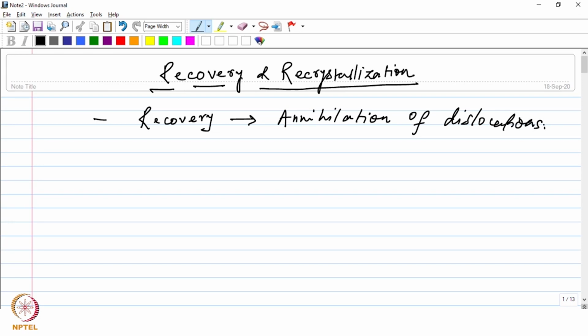When the dislocations get arranged in some low energy configurations, the dislocation density is going to reduce, and the regions around this arrangement will be free of dislocations, right? So that's how the recovery occurs as you heat the material to some elevated temperature. And once the recovery process starts, as you continue to heat the material to higher temperature, then the recrystallization process starts. So this is when the restoration of the material will take place, and the straining which was given to the material during cold working will be relieved.